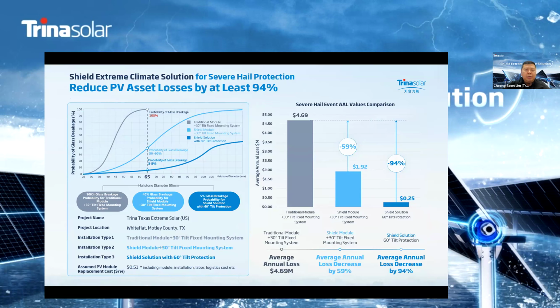So this is a calculation study that we have done on glass breakage under different hailstone diameters. You can see we have done this study in a multi-county area in the US. This is a comparison between 3 different installation types: the standard module plus 30 degrees fixed tilt system, then the Trina Shield module plus 30 degree fixed tilt system, and then the Trina solution with the 60 degrees tilt protection. You can see here the probability of glass breakage at hailstone 65 mm.